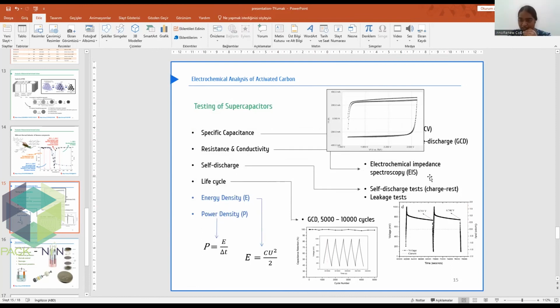How does the purity of the crystalline phase of active material affect the capacitance? Actually, I don't know this, because biomass, as you know, is not a pure material - it is very heterogeneous. We made some experiments, and I guess when you increase the homogeneity, the specific capacitance will increase. But when you use the homogeneity of the electrode, the specific capacitance increases while other parameters like self-discharge and resistance can decrease. So if your purpose is to increase the specific capacitance, you can do it with a homogeneous electrode. But if we're talking about total capacity performance, the resistance can increase, and we don't want this.